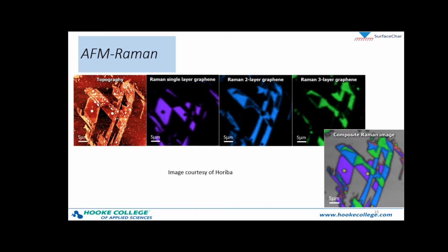But it turns out in this flake there was some single layer, 2-layer, and 3 layers of graphene that the Raman signal is particularly suited to resolve, because each of these different layers, however many layers of graphene you have, has different signatures or peaks in your Raman spectrum. And so, correlating with this topography image, they were able to collect Raman signals, just focusing in on the peaks of the different single, double, and 3 layers of graphene, and could then put a composite together and map out, with this topography, where these different graphene thicknesses were in this flake, which you would never be able to do from just the topography alone.